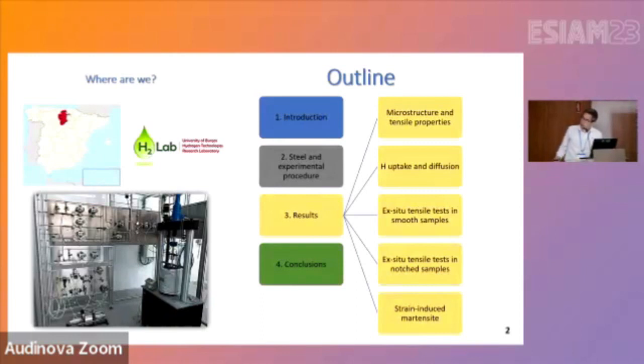The laboratory is equipped with a high pressure, high temperature hydrogen facility, able to work up to 300 bars and 300 degrees. It's also possible to blend gases. Among others, the laboratory is equipped with a high pressure hydrogen permeation facility to evaluate trapping and hydrogen diffusion kinetics. We also have a hydrogen leak analyzer to determine the hydrogen concentrations.